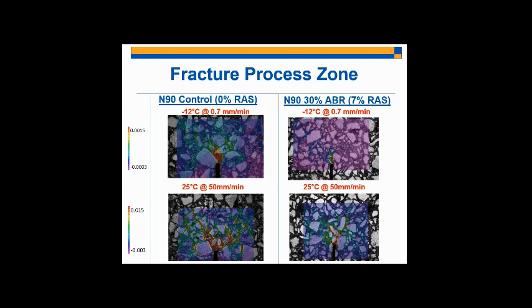But at 25 degrees Celsius, there's a kind of diffusion of the fracture process zone further out into the specimen, and you can see that it's much more prominent in regions further away from the crack tip. And so we can conclude from this that basically the effect of shifting the temperature from -12 to 25 C is a diffusion of the fracture process zone. And we hypothesized that basically in the field, what's happening is something similar to the 25 degrees Celsius testing condition, where the fracture process zone is much more diffused throughout the bulk regions of the material, of the asphalt pavement.